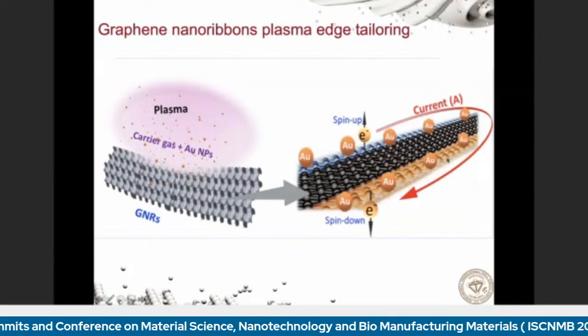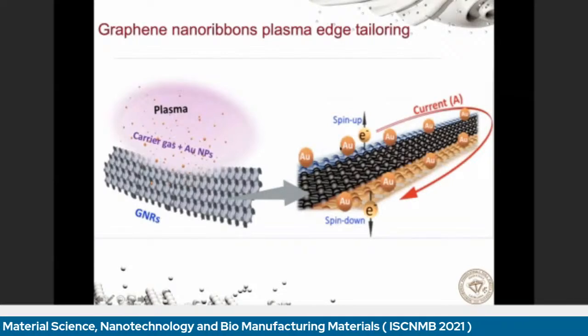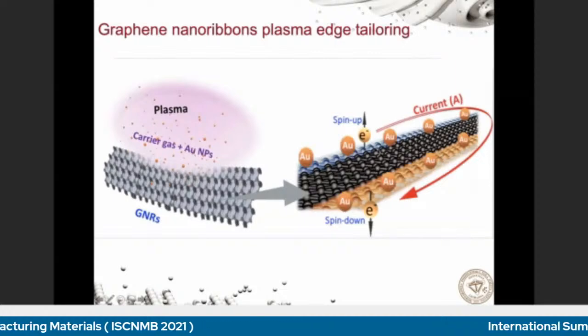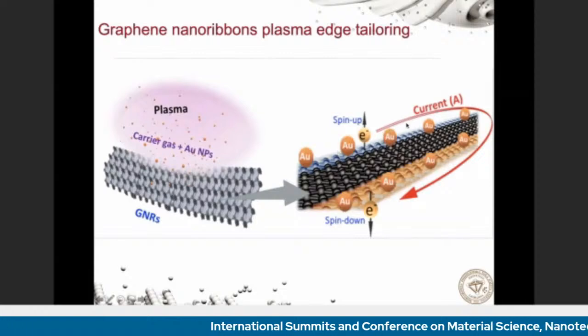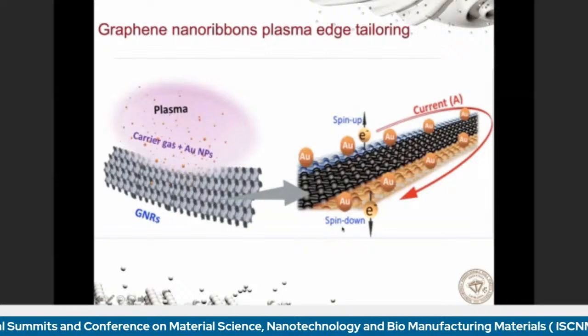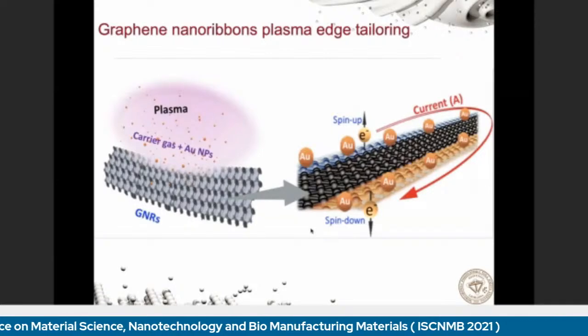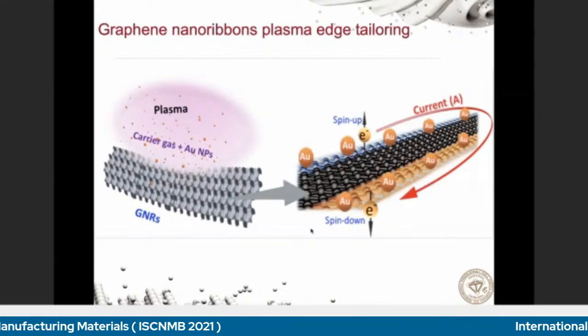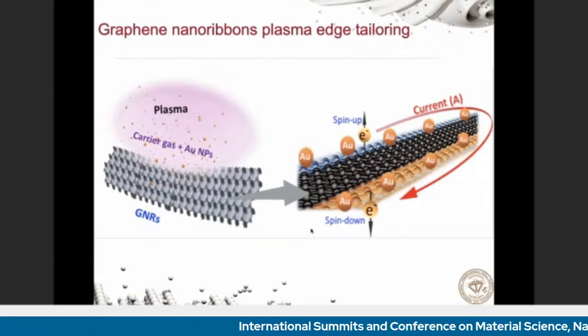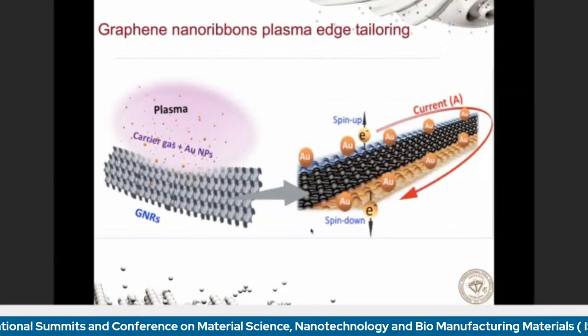So on the right-hand side, you can see here the graphene sheet. The gold atoms are attached to it, and this attachment of these gold atoms actually modifies the spin properties, the spins of electrons, which then causes the electric current to go in one way around this. You would call this small piece of graphene a kind of nanoribbon of graphene. And that's, of course, a very promising application for electronic devices because they have current flowing only in one direction. And that's how you can actually modify the properties necessary for electronic devices.